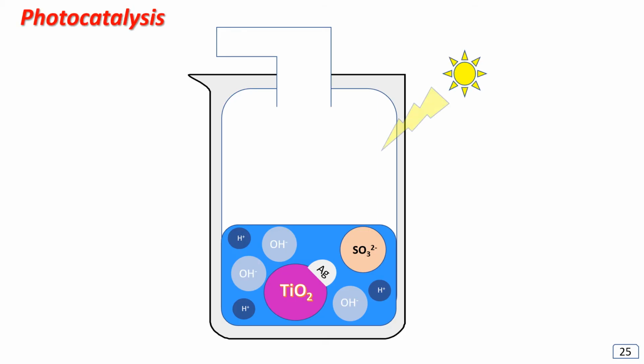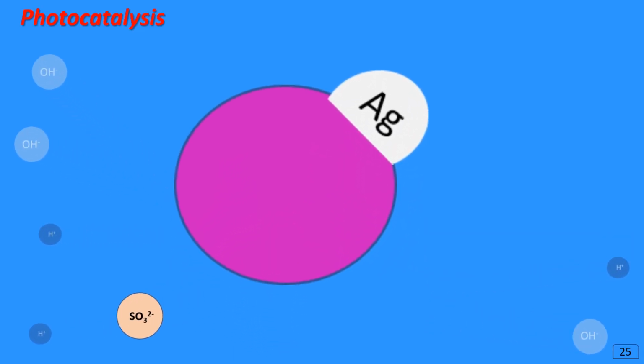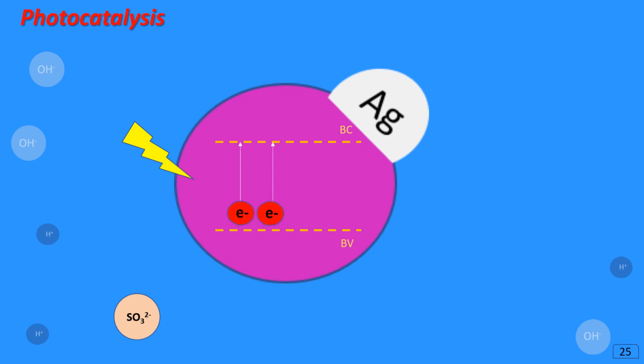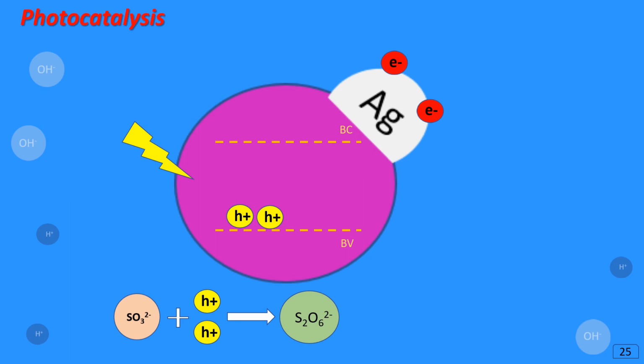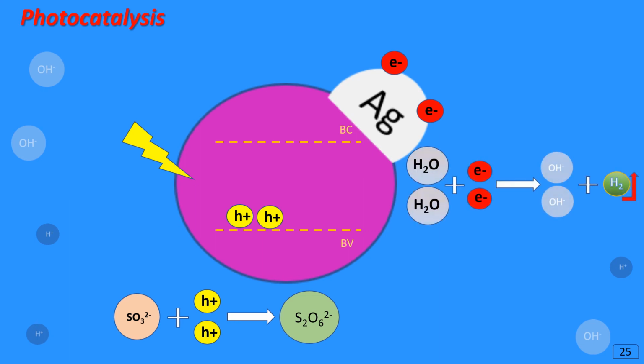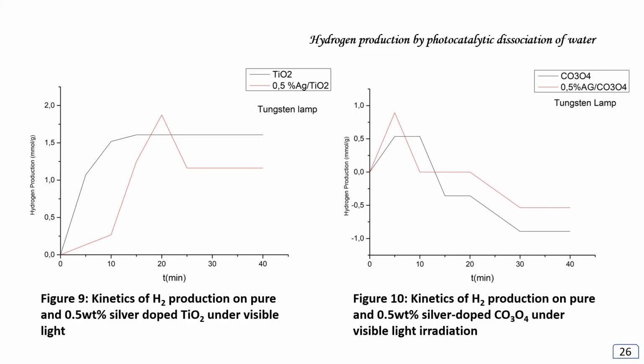The irradiation of the photocatalyst causes the departure of electrons from the valence band to the conduction band, leaving holes in the valence band. The electrons will migrate to the surface, and the holes oxidize SO3 2-, and the electrons reduce the water to give hydroxide anions and hydrogen. These figures show the amount of hydrogen produced as a function of time.